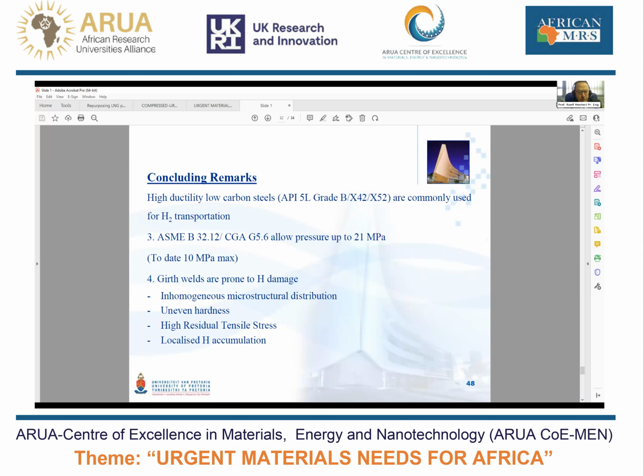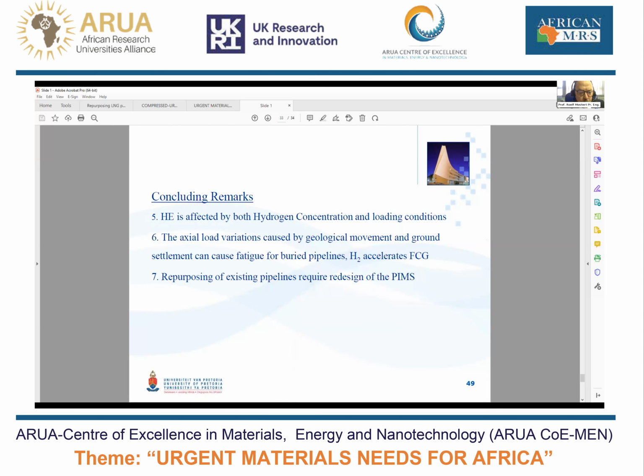So the girth welds are prone to hydrogen damage due to a number of factors such as the high residual stress levels. So the hydrogen embrittlement will be affected by both the concentration of hydrogen and also the particular loading conditions in the pipeline. And the actual load variations that you will get in the pipeline due to geological movement and the like can cause fatigue for these pipelines. And as I said, it's known that hydrogen accelerates the fatigue crack growth at high enough hydrogen pressures.